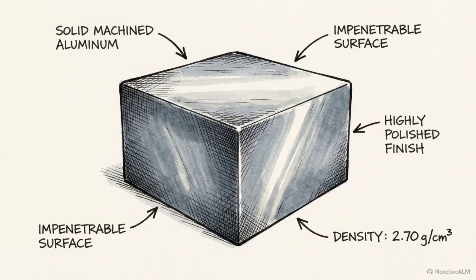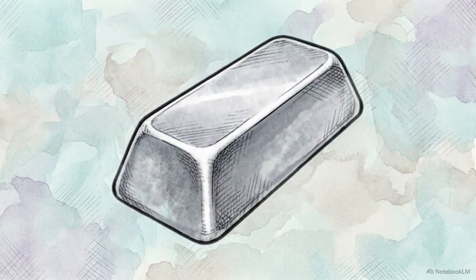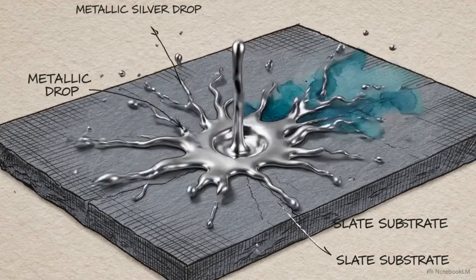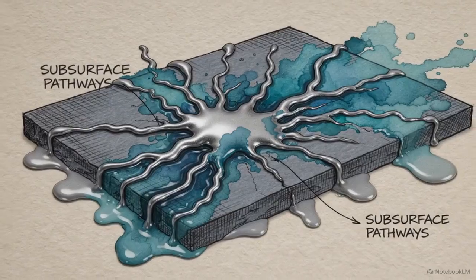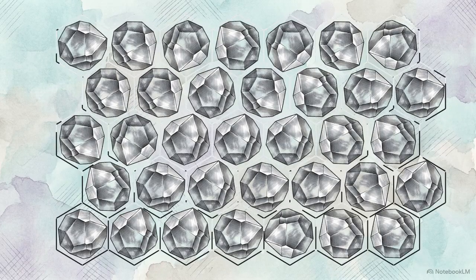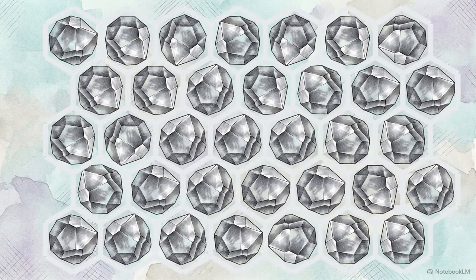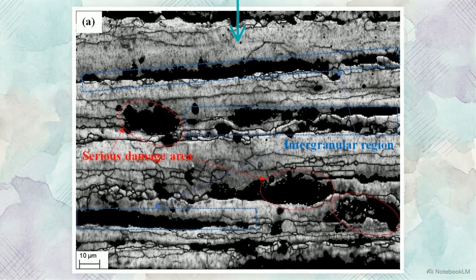To see how this happens, we have to look at aluminum at the microscopic scale. A solid block of the metal is actually a mosaic of billions of microscopic crystalline grains pressed tightly together. When liquid gallium touches the surface of the metal, it acts exactly like water seeping deep into the tiny cracks of a dry pavement. It continuously infiltrates the microscopic boundaries between the aluminum grains. In this microscopic view of an aluminum alloy, you can see this structure in detail. The blue areas identify the intergranular boundaries, where the gallium enters, leading to the severe damage marked in red.